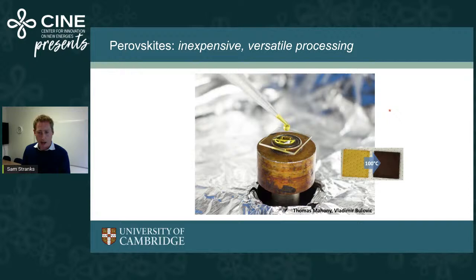When we process them in the lab, and those of you working on perovskites will know this well, typically they're processed with solution processing methods. There are some vapor methods as well that I won't talk so much about today. Typically from inks of these precursor materials, the precursor salts are dissolved in solutions, and these are spin coated at a few thousand RPM to form very uniform films, and then heated relatively gently at 100 degrees Celsius to form very crystalline semiconductors. And this is what makes the solar absorber.